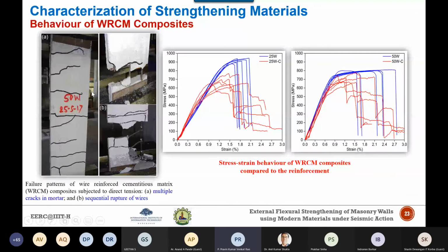For a majority of these specimens, the failure was caused by the sequential breaking of the wires inside the cementitious matrix, but very few specimens showed tensile failure of wires near the gripping area. Here the blue lines show the test results of the dry reinforcement, whereas the red stress strain curves, or load displacement curves, represent the composite specimens. There is a reduction of 11% to 25% in strength in comparison with the dry wire reinforcement, whereas the initial stiffness is almost a close match. This reduction in strength can be attributed to the sequential failure of the multiple wires present in the coupons.